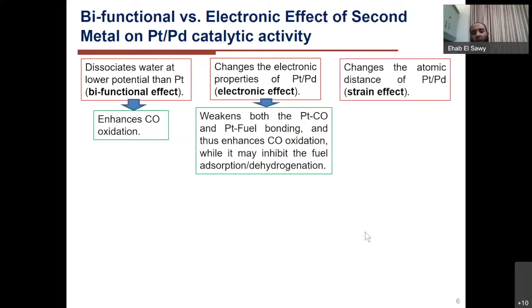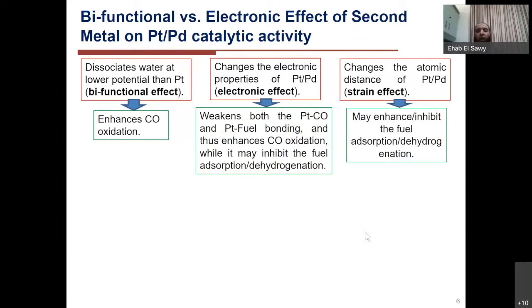And the last is the strain effect. So if we are adding a second metal that has a different atom-atom distance, that again affects the platinum-platinum atomic distance or the palladium-palladium atomic distance, and that may affect the adsorption and dehydrogenation of the fuel and converting it to the product. So in the case of alloy, as I mentioned, all these effects are mixed together.